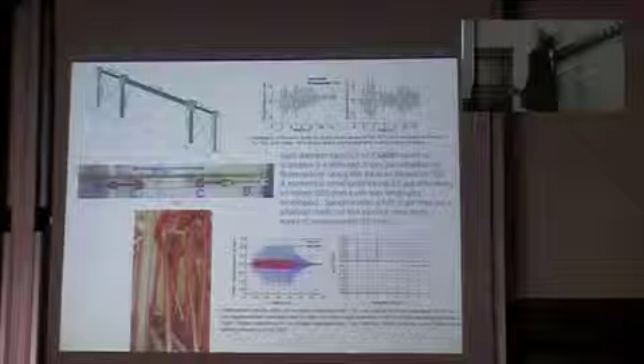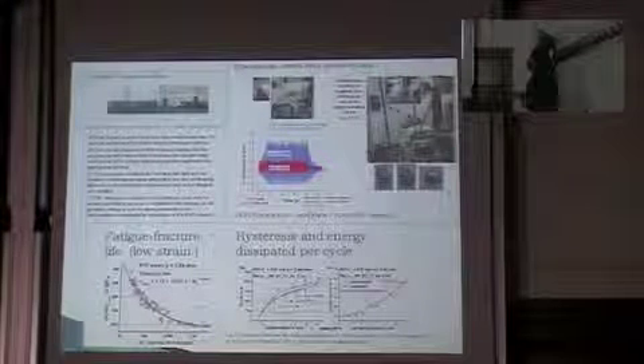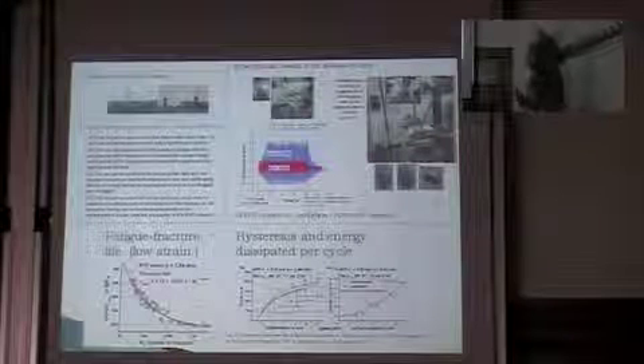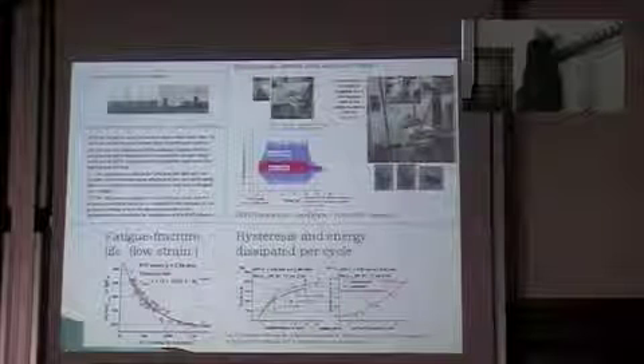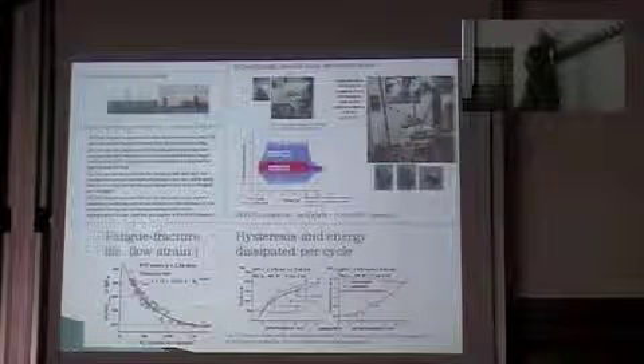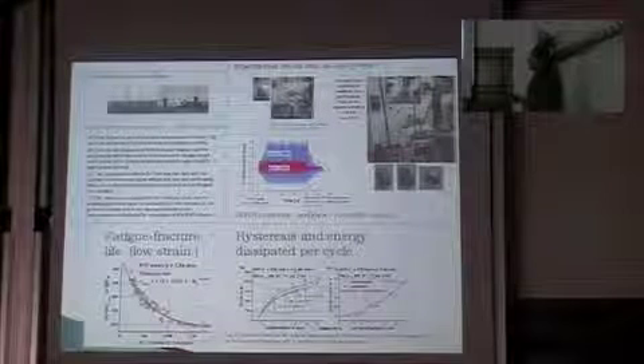So this one was a seismic application. Here is the application for cable stays in bridges, which has different requirements because the problem is very different. The number of cycles that the structure needs to survive in this kind of application, the fatigue life, must be much longer than for an earthquake. But on the other side, the deformation levels that you're working with are much lower. So in any case, you can still survive 1 million cycles with this device using the entire fatigue life. Also notice you cannot rely anymore on the big entire cycle that you had for the earthquake case, because when you go in earthquake, the maximum deformation here is around 8%. So you're relying on a bigger cycle. Here, when we have wind application, the deformation is about 2% or lower. So you can rely on smaller energy dissipation capacity.